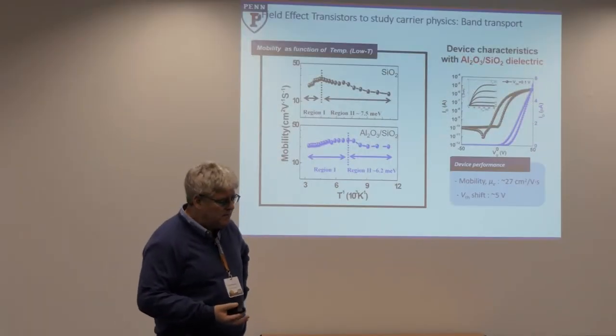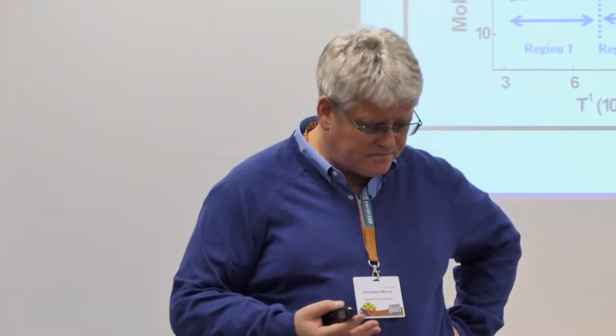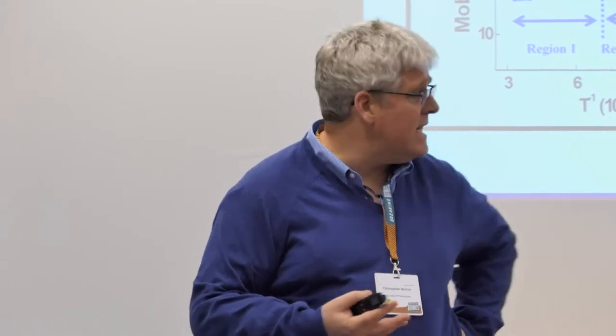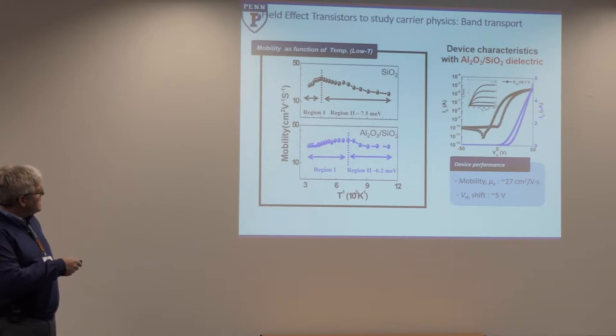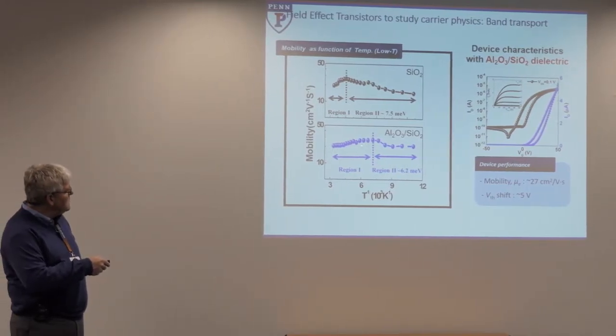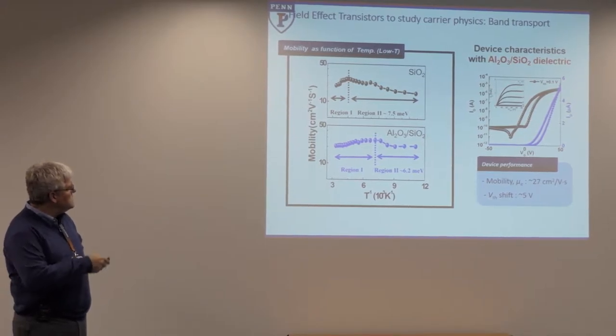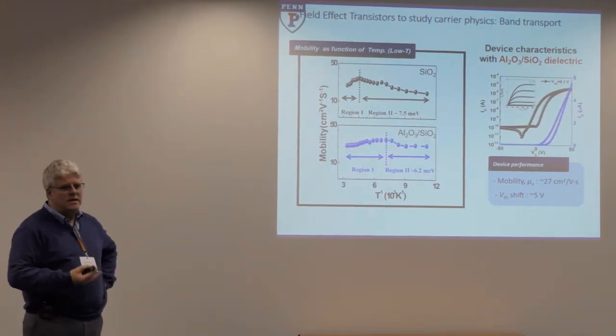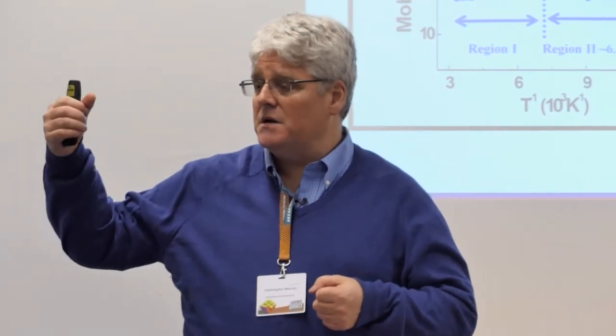That thiocyanate group was a lead option in terms of transforming conduction in these quantum dot solids. The data that I'm showing here, sorry, it's a little arcane to be plotting mobility versus, actually that should be inverse temperature, pardon me. But this plot and this peak, even though it's not so dramatic looking, is actually very important. What this is showing is that the mobility in these materials gets better as you go lower in temperature. Why that's so important is that if you're in a regime of hopping transport, that mechanism requires thermal activation to move from one particle to the next. So the classic hallmark is that mobility improves as you increase the temperature, because you have that extra burst to get over the barriers that are getting in the way of charge transport.